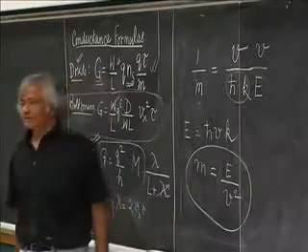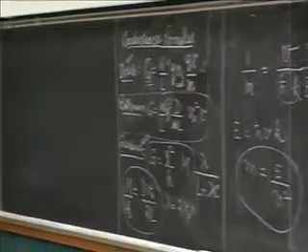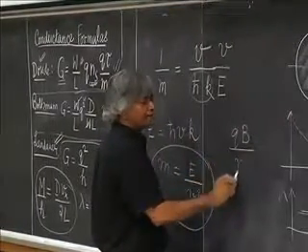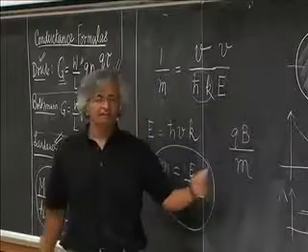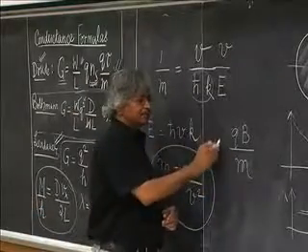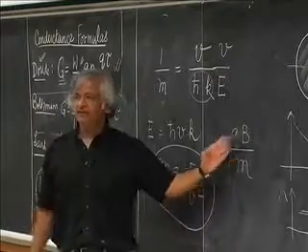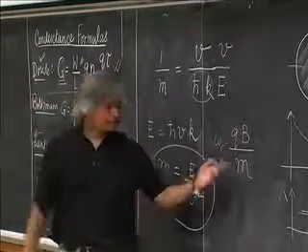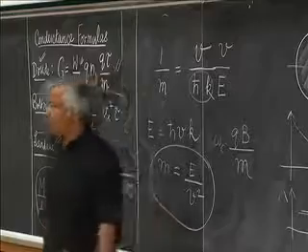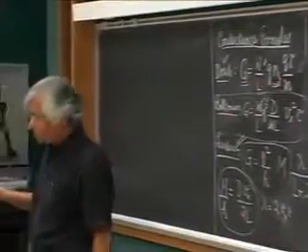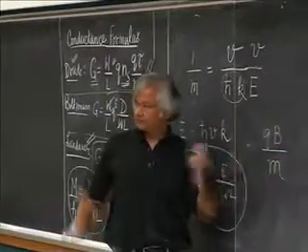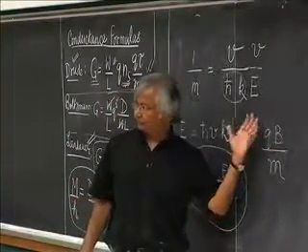And what they find is, while in ordinary semiconductors, as you change the energy, the cyclotron resonance frequency is supposed to be QB over M. As you change the magnetic field, the cyclotron frequency changes like this. And usually in a normal semiconductor, that's independent of the carrier density. If you change it, same mass, fixed resonance. Whereas in graphene, as you increase it, the cyclotron frequency actually goes down. That's an experimentally measured fact.